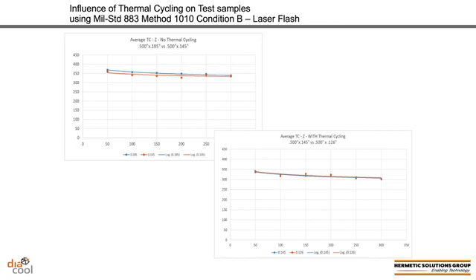You can see that there's very little difference between the two. The difference is minimal, roughly around 5%, essentially, if you will, a settling in of this material. And as I tested this material even past 60 cycles, I saw no degradation of thermal conductivity even beyond 100 cycles. So the material is very stable in these kinds of cycling conditions.